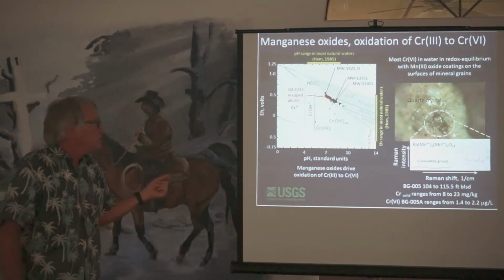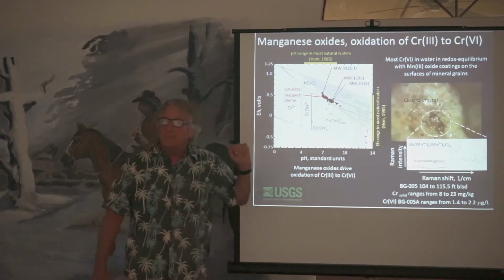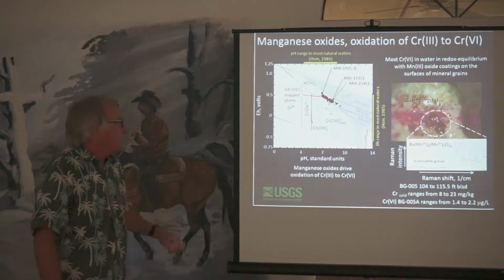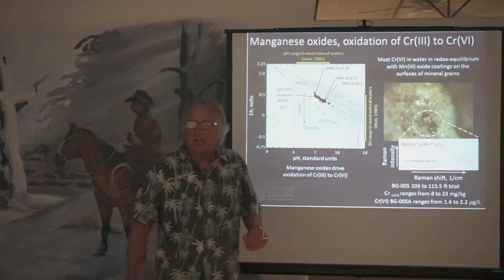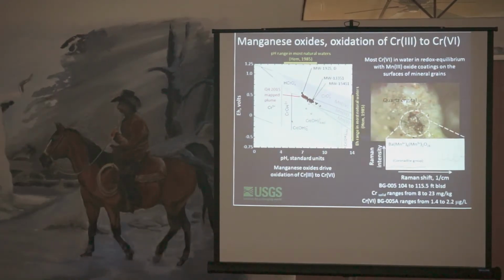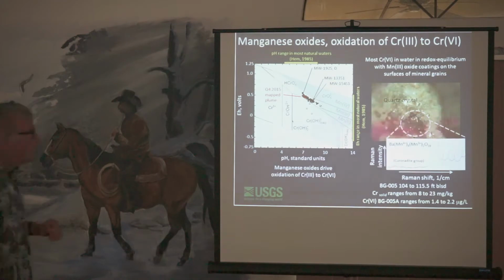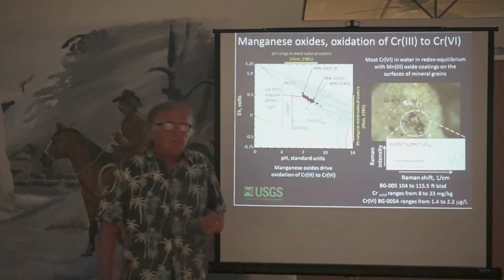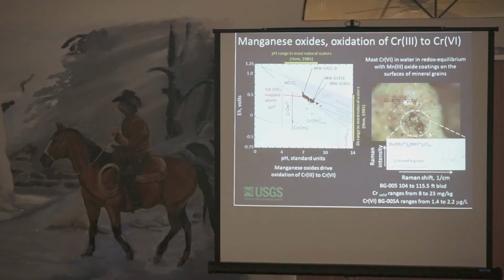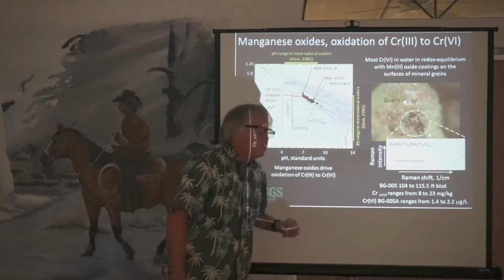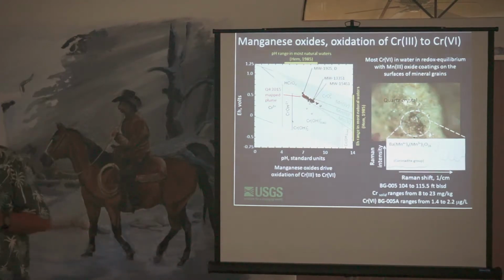If there's manganese present, and particularly manganese 3, it can be oxidized to Chrome 6. And here's what we're looking at right there. That's an optical image of a quartz grain. That little black speck that you see there was analyzed using a Raman spectrograph, which looks at the vibrational modes of the electrons on there. And we know it's a cryptomelane group mineral. It's actually, I think, hollandite. It's a manganese 3, manganese 4 oxide. It's quite capable of taking Chrome 3 and oxidizing it up to Chrome 6.